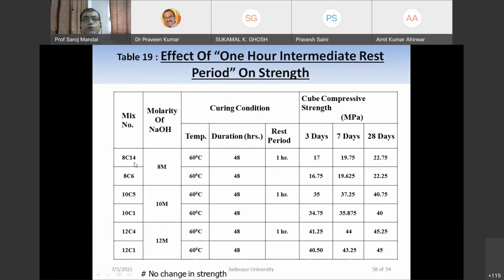Now you see, we have put this as the mixes. This is the 1 hour rest period and there is no rest period. There is total continuous 48 hours, with a 1 hour rest period, right? So if we put a 1 hour rest period, the strength is almost the same. Strength is almost the same. You can see for the 8 molar, 10 molar and 12 molar, right? So we can say that if we make this rest period of 1 hour for removal of the mold, we can get some advantages. There is no change or reduction in strength.